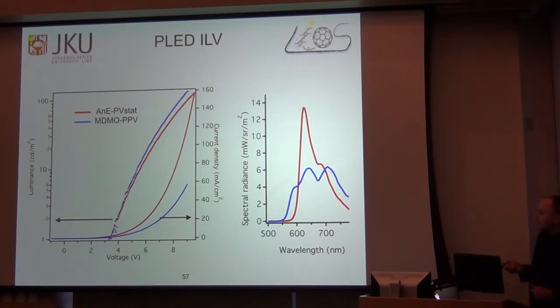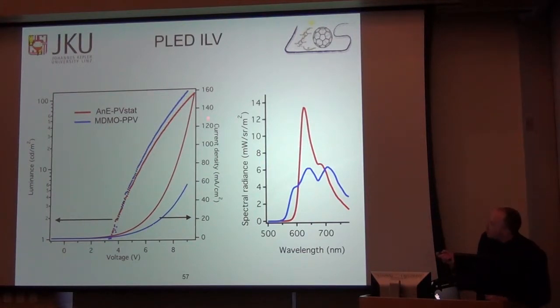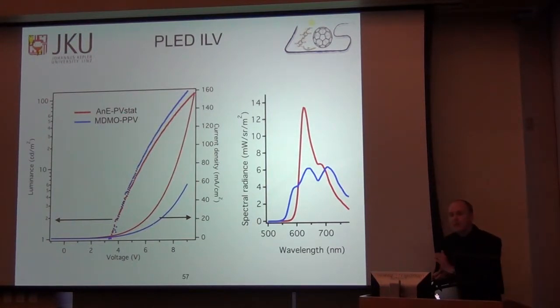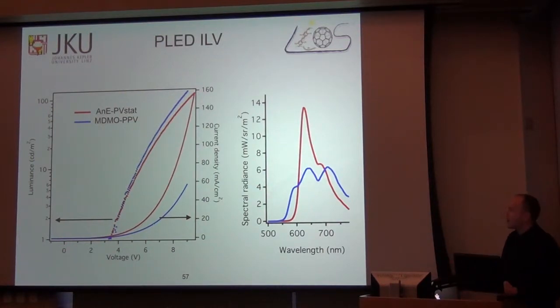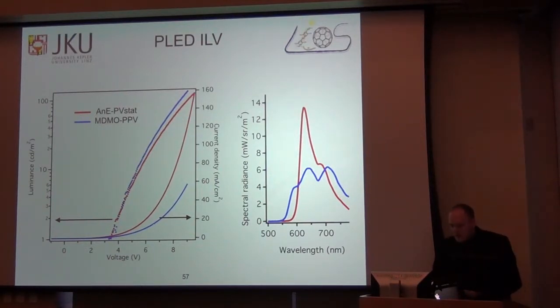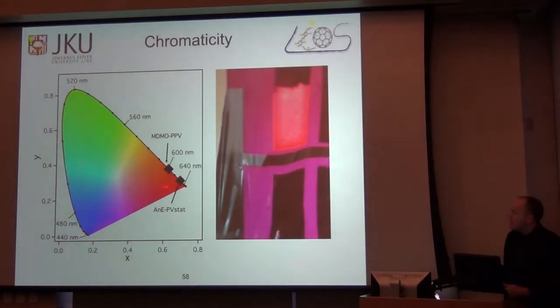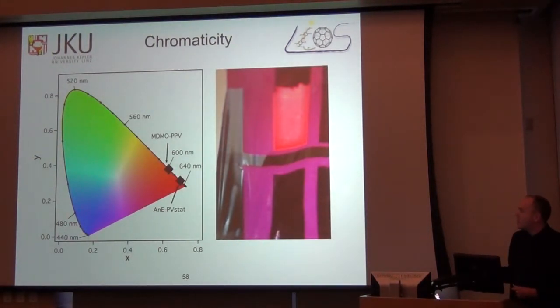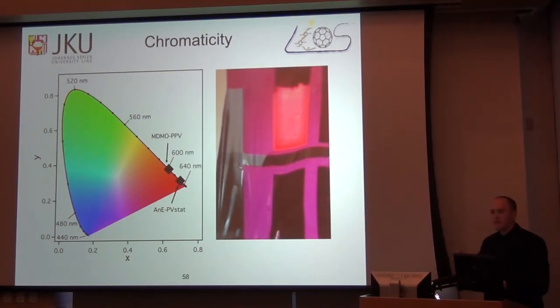The current voltage and the light intensity voltage curves of the LEDs are shown here. Both devices, both colors, reach an intensity threshold of about 100 candelas per meter squared, which is about what you would need for dim indoor display applications. They're not particularly bright, but they are functional. And here you can see the two spectra coming out. Here I plot the two colors on the XY chromaticity diagram, and you can see here one of the red LEDs operating in what I call freestanding foil configuration, where this foil is just floating by itself.